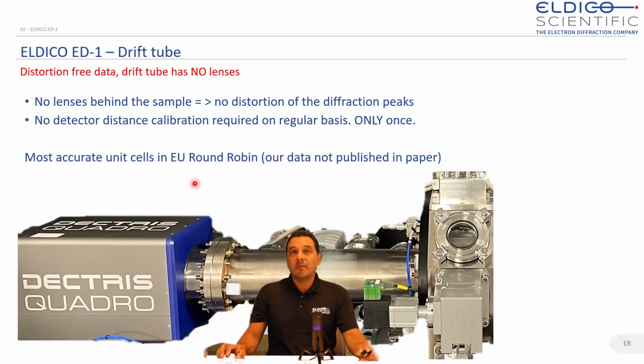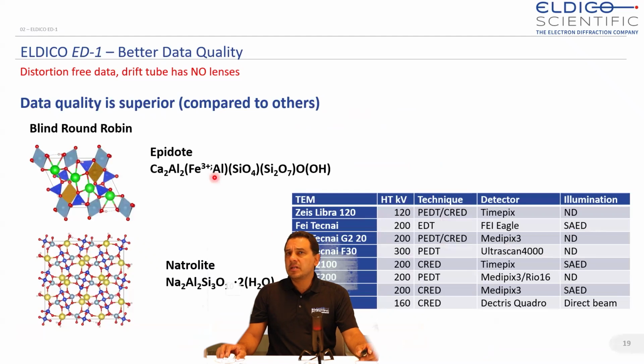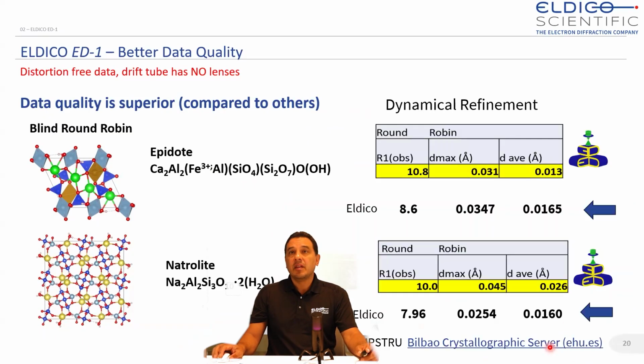Now, indeed, there's a study from the electron diffraction community, the non-ED, who have taken this into consideration and have done a round-robin study. Now, let me show you the results. They should be coming soon, or probably they are being published at the time we speak. They have tested different microscopes in the different facilities that can produce electron diffraction. And you see there the device that was tested and the method that was used for obtaining a structure. Our device was also part of the test. And at the end of the day, indeed, our device shows better results than the average of all those devices that have been used there in this round robin.